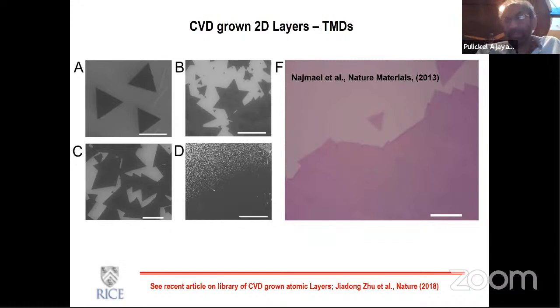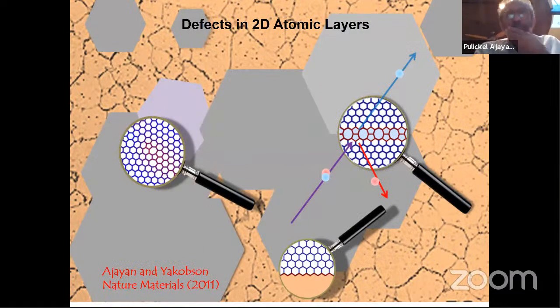We were able to grow very large area structures as early as 2013, and a lot of people have followed this approach to make large area systems of these materials. Now, one thing to notice is that defects, of course, become very important, and it's quite hard to control defects. We were also interested in looking at what kind of defects exist in these materials, what kind of grain boundaries form in these structures, and so on. Graphene is a very interesting example because a lot is known about defects in carbon, particularly these topological defects.